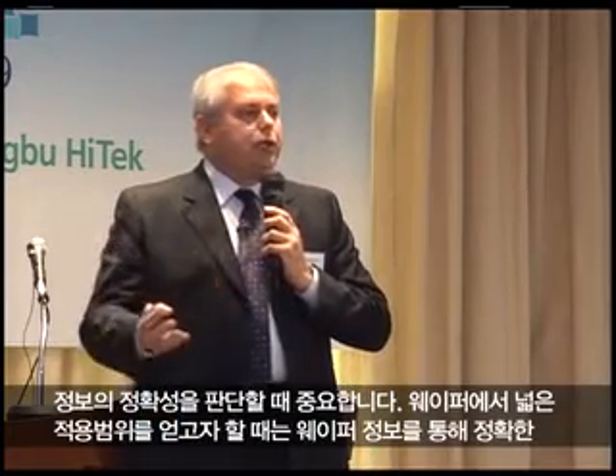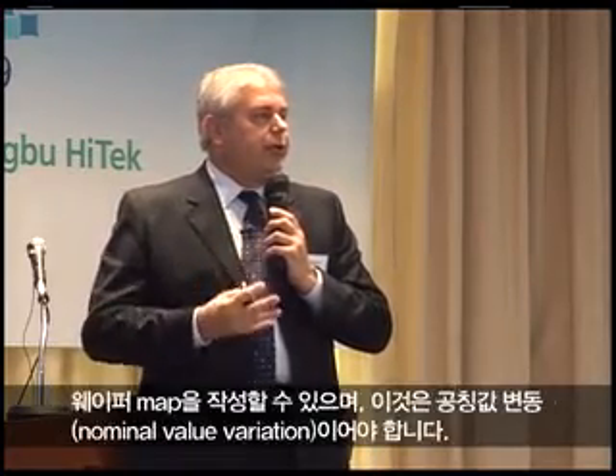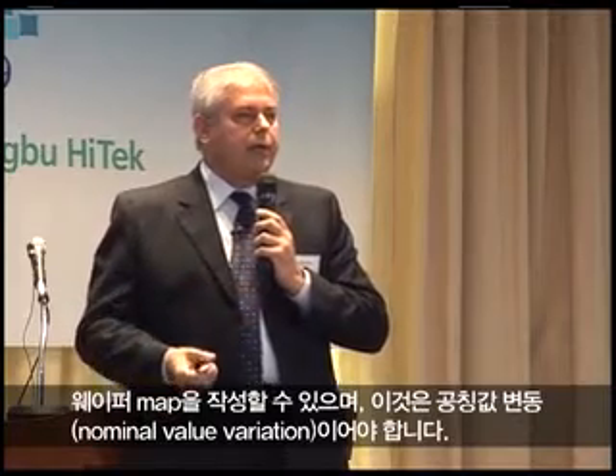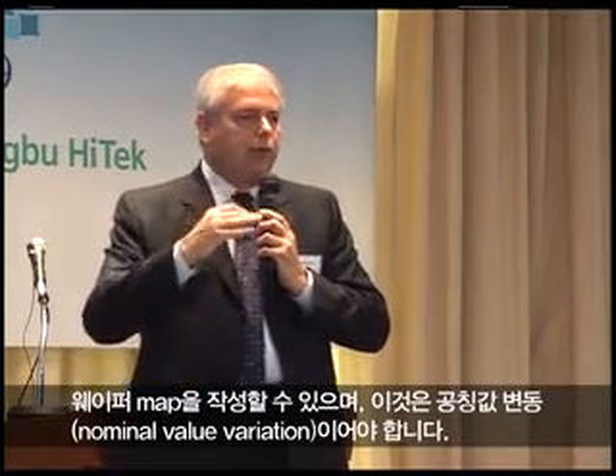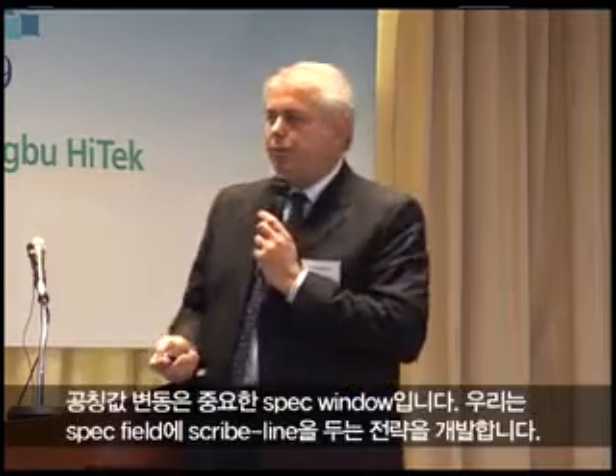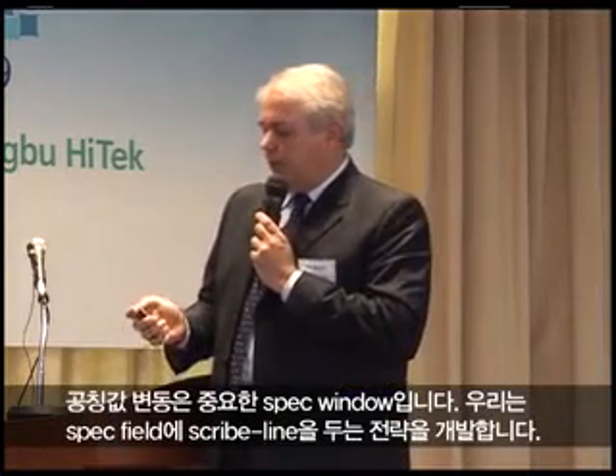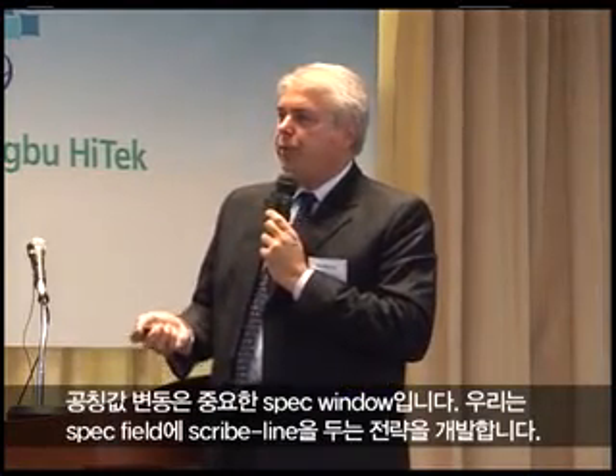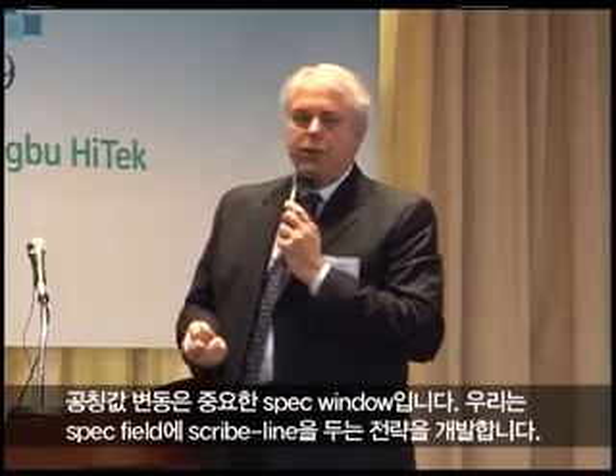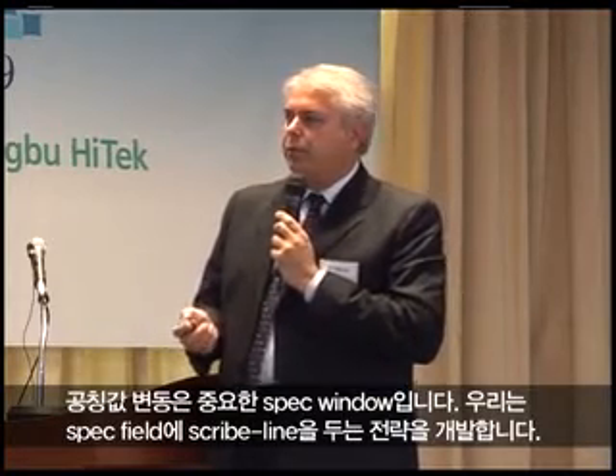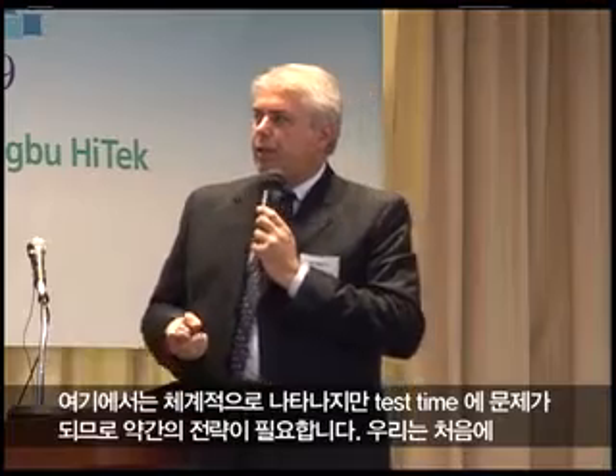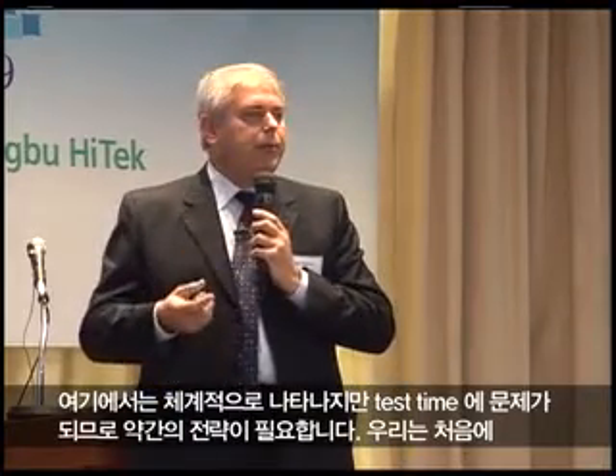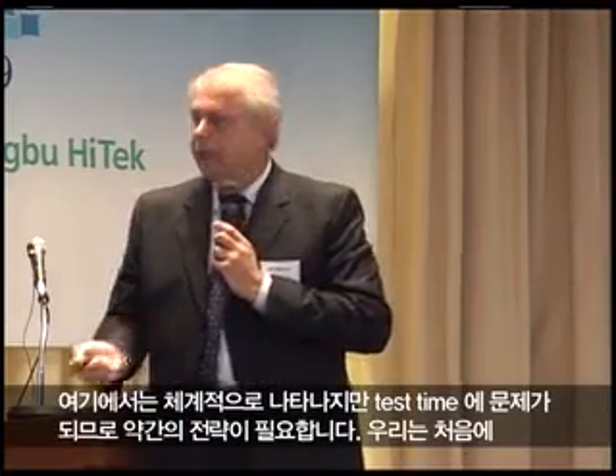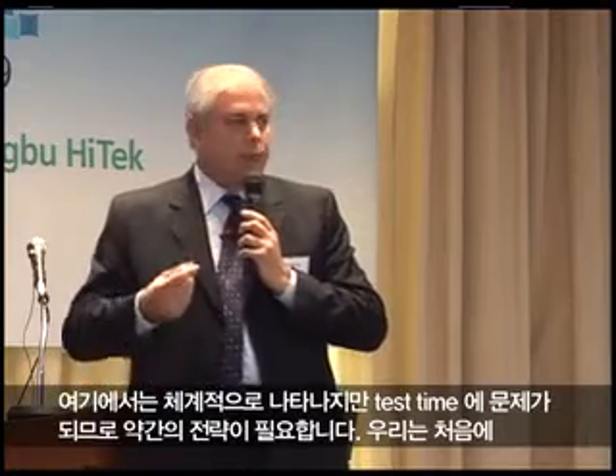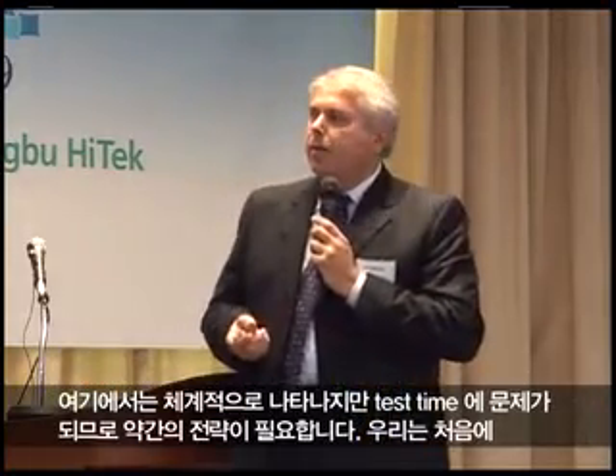To get broad coverage across the wafer so that we can do an accurate wafer map of the across-wafer information, which has to do with the nominal value variation, which is important to the spec window, we've developed strategies of putting scribe lines across the stepper field that are schematically shown here. And then this becomes a problem in test time, but we have some strategies there as well.